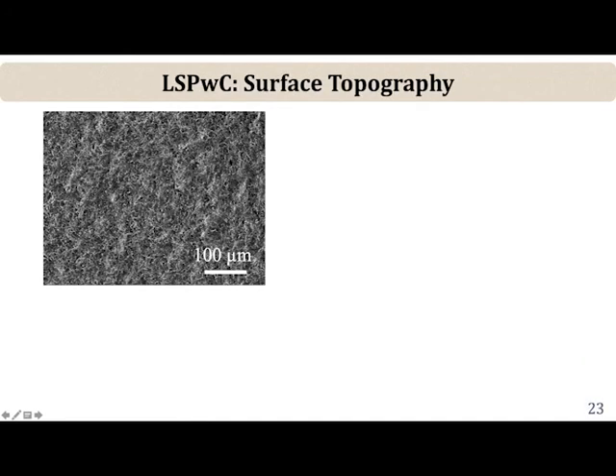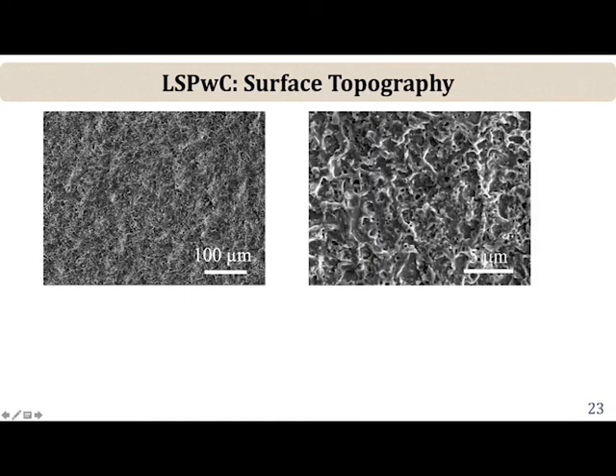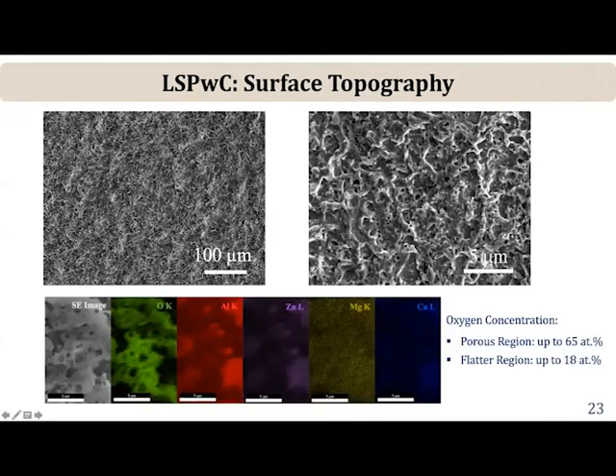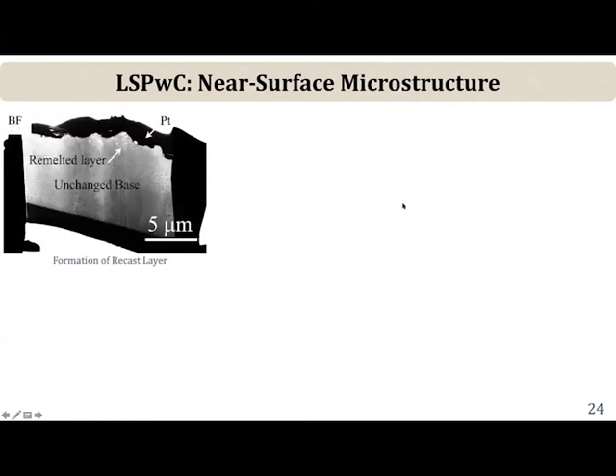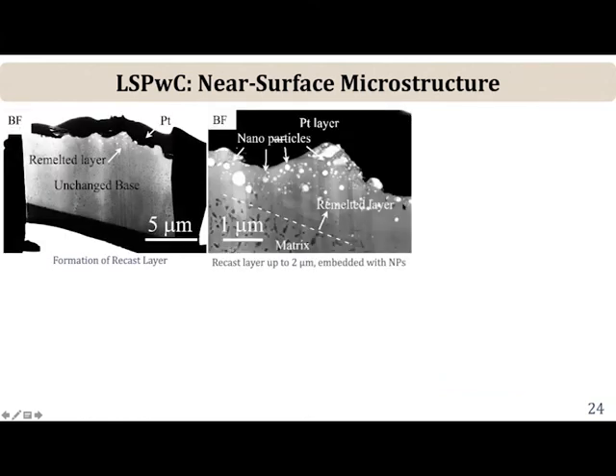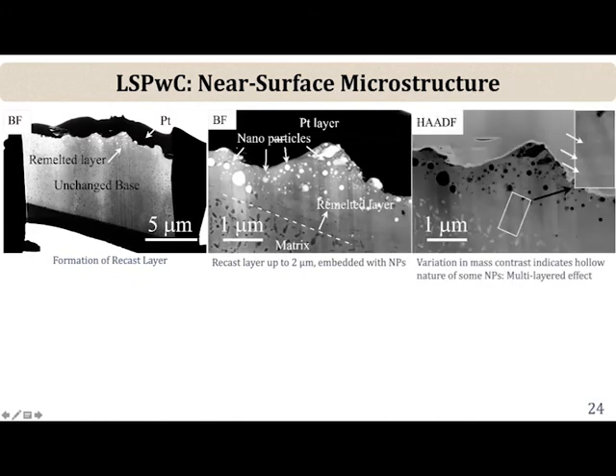Okay, so when you do this surface laser peening without coating, you get a fairly rough surface, and you can see here what looks like even some particles and some blowholes and so on. But when you measure the oxygen in some of these porous regions, the oxygen content on the surface is fairly high, on the order of about 65 atomic percent in some cases. So we FIBbed out a foil from the near surface region. So this is a lamella cut through the surface. Okay, so what you see here is after laser shock peening without the coating, you have a region where you have the base microstructure, which is shown here, which has the MgZn2 precipitates.